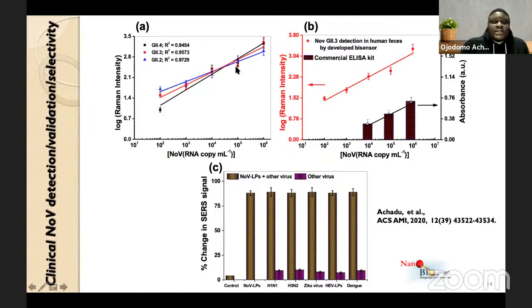The norovirus were extracted from different clinical fecal samples, and we collected different concentrations, and we're able to quantify with this very system. Then for validation, we compared the sensitivity of our method with a commercially available ELISA kit for norovirus detection. And we found that, yes, the system can detect norovirus more sensitively compared to the tested ELISA kit.